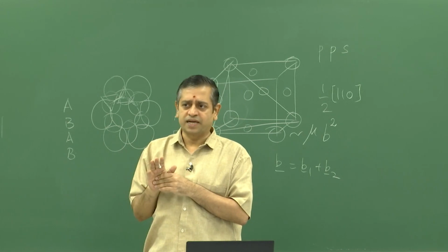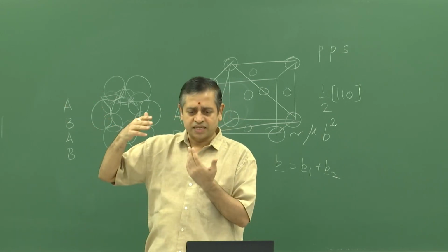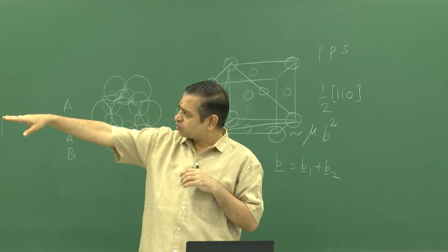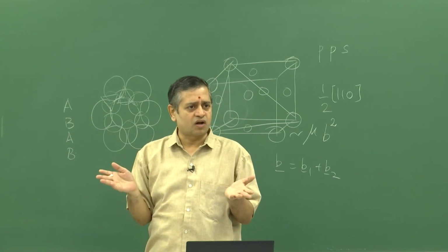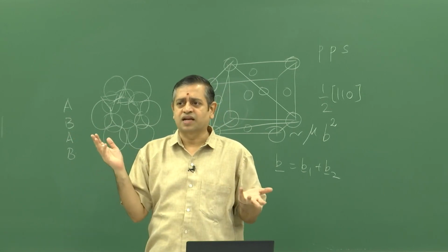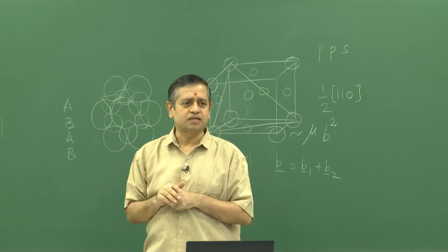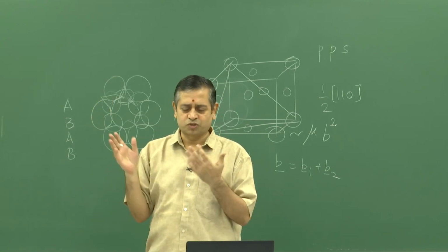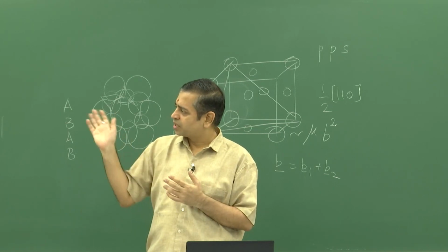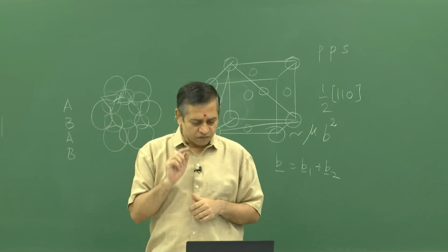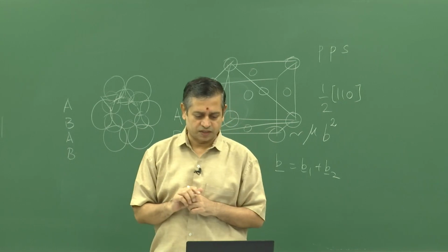and you can get the GSFE curve, which also agrees with this PPS. I mean, in the PPS case also, if you put the surface quite close to the stacking fault, you will get wrong answers there also, because the surface will relax. It has to be far off, so that what happens at the boundary is not important. So, you can put shrink wrap, you can put periodic boundary condition, you can get the same results, which is what is shown in the next figure.